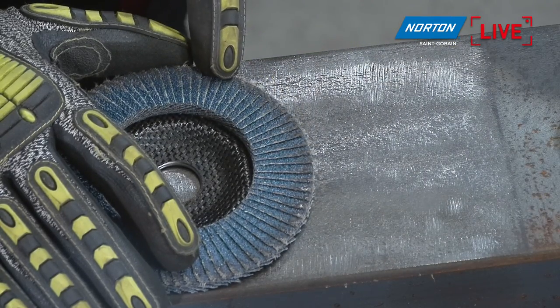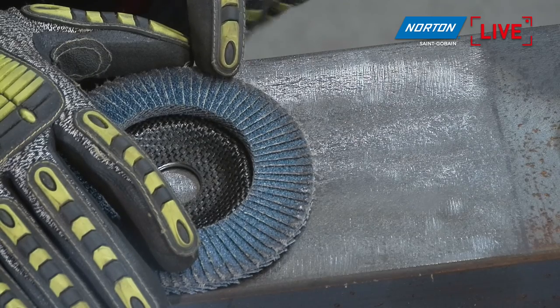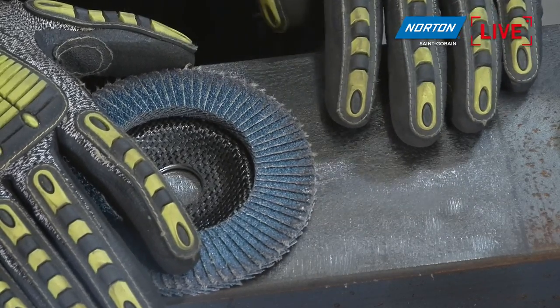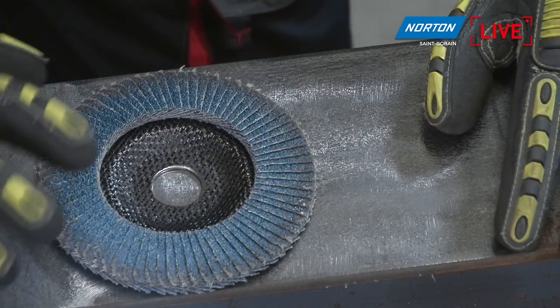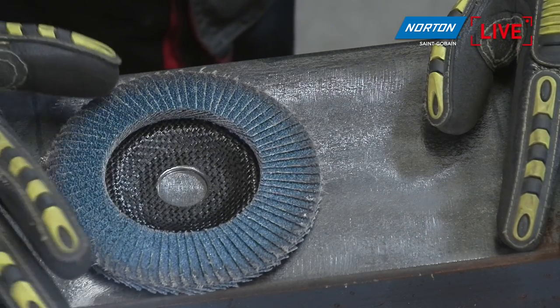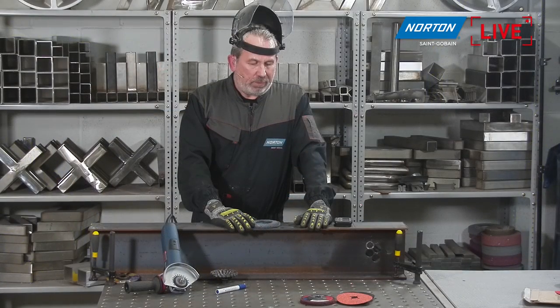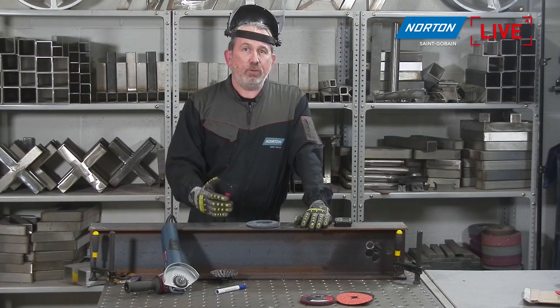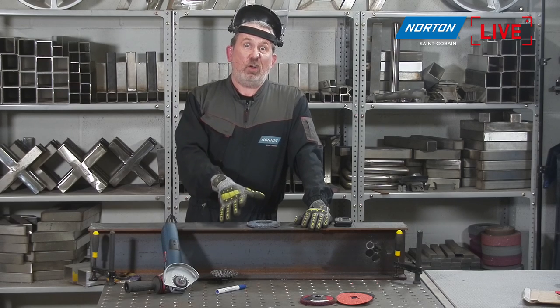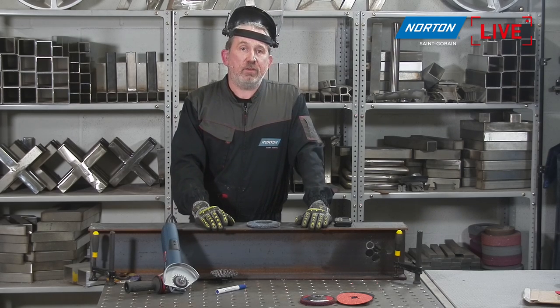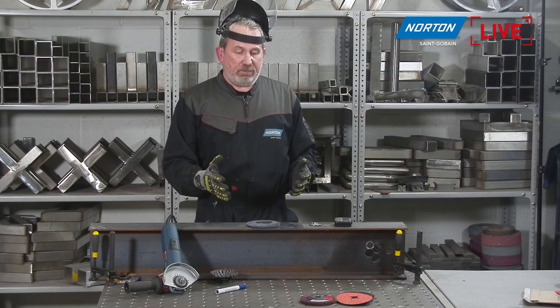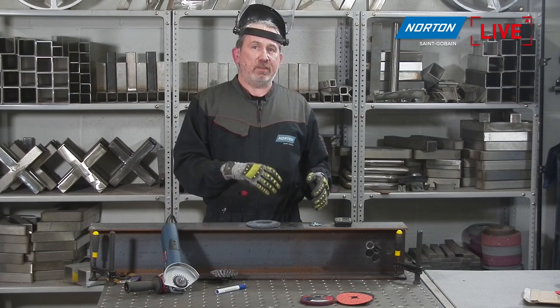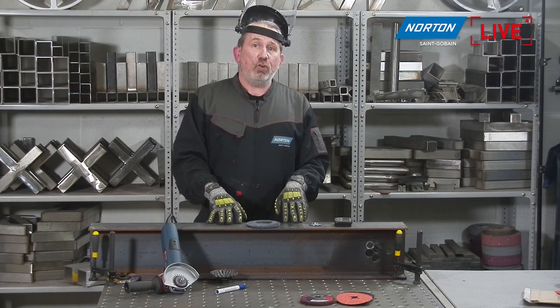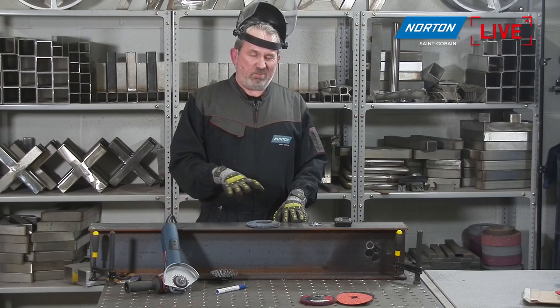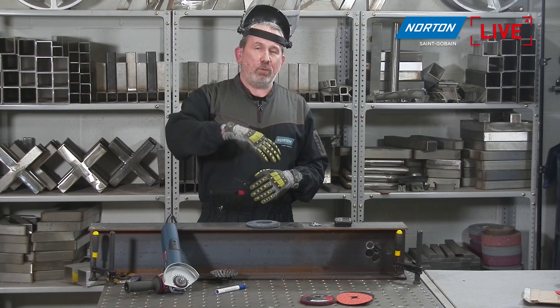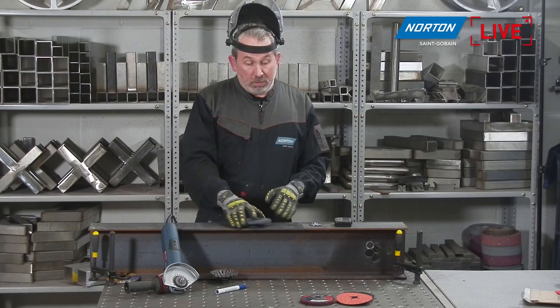So we're starting to have a problem, what we call loading. That's where the ground substrate that we are trying to remove with the product is actually sticking to the disc itself. Not a problem if you're using that product for a couple of minutes, but if you continue to use that product and the loading gets worse, that stuff that's stuck to the edge of the disc will actually stop the disc working. You'll start to feel the disc sliding over. So whilst it does a good job in the first instance, after a few minutes of use, the cut rate will probably start to drop down, but decent job.